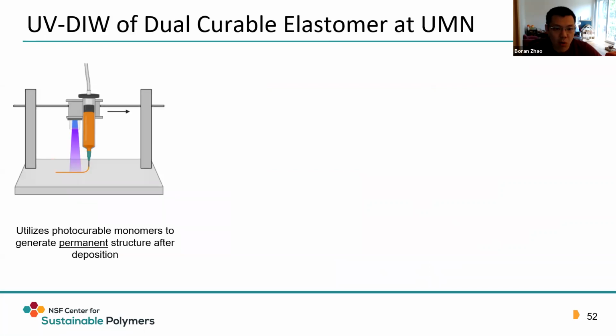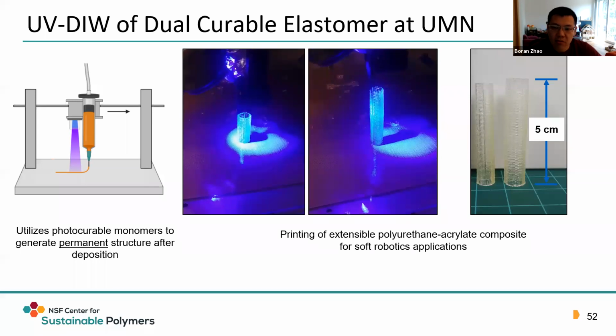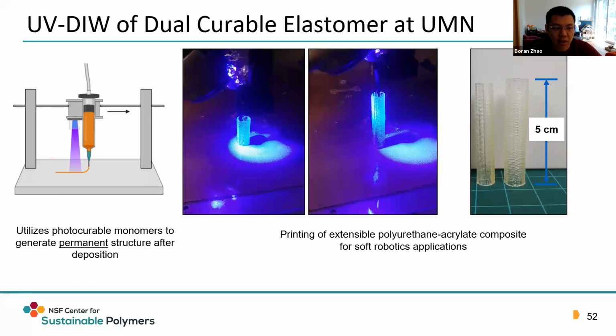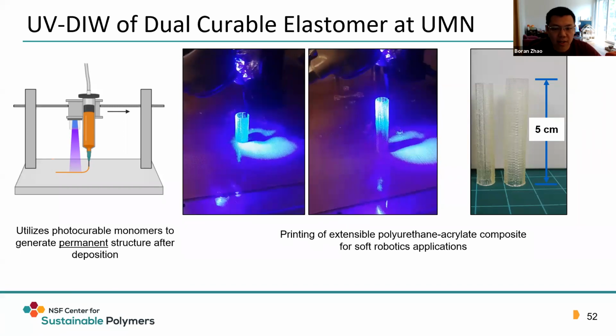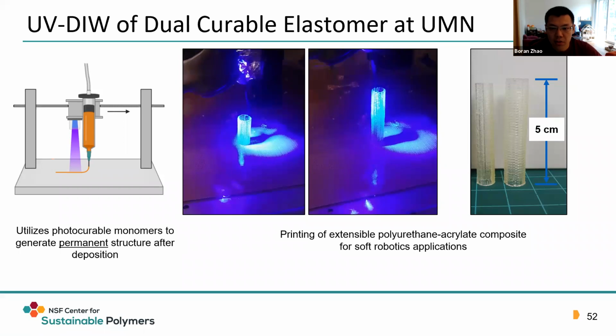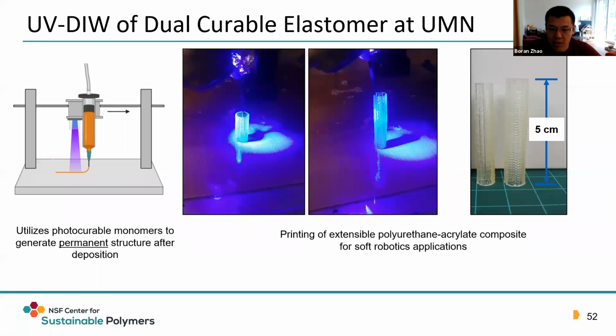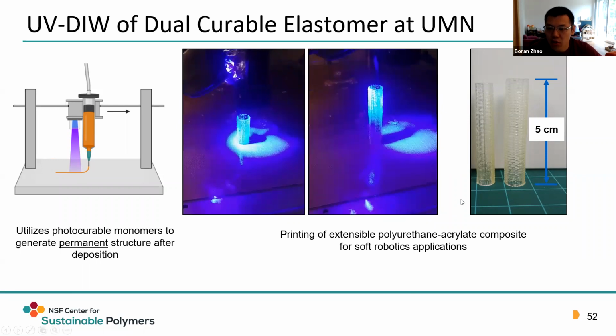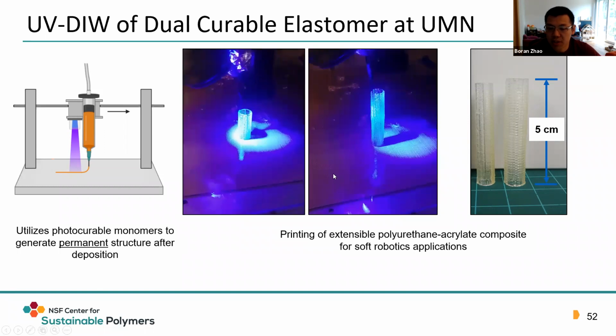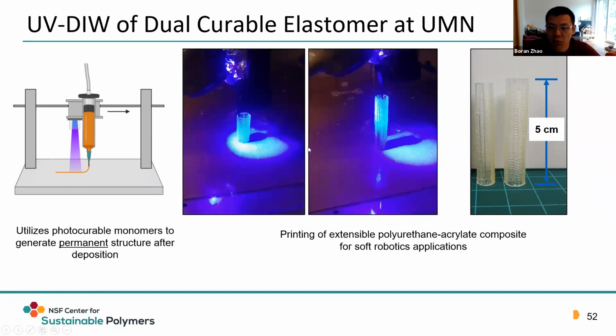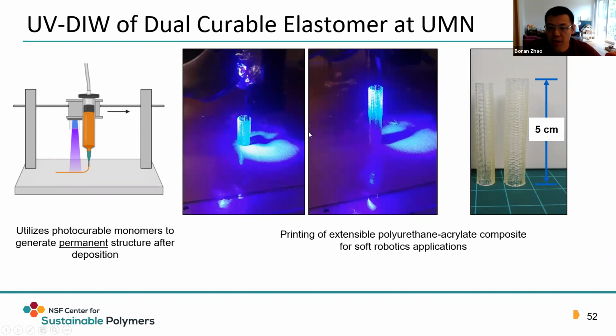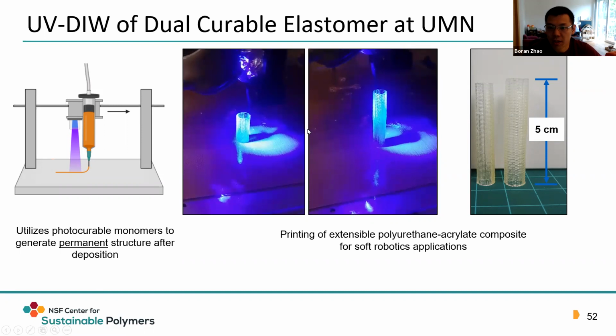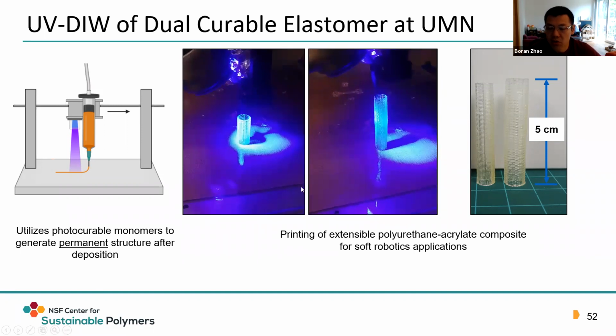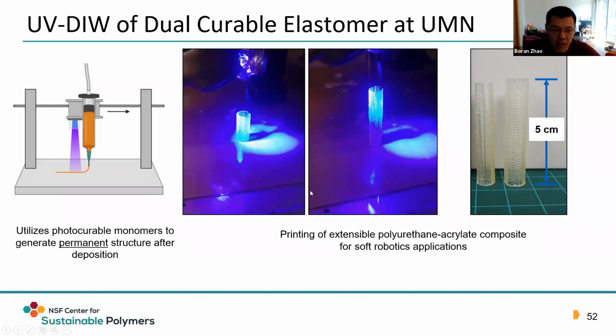Here's an example of work done at UMN, from Professor Allison and Professor Francis' groups. We developed a dual curable resin from acrylates and polyurethane. The green body is solidified by UV curing the acrylate component, and the polyurethane component is cured afterwards in a thermal heating process. As shown here, we can generate fairly high aspect ratio elastomers, and depending on the ratio of acrylate to polyurethane components, the print could be as rigid as a solid body or as extensible as an elastomer—perfectly suitable for soft robotic applications.